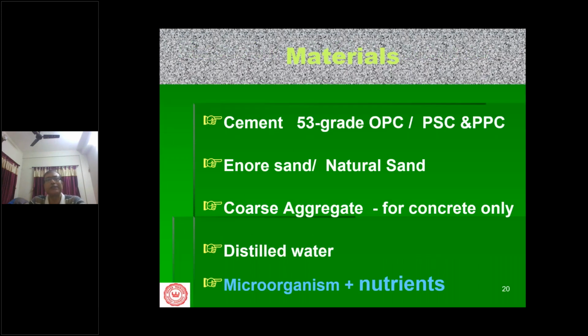Now, after getting this, we started adding it within the concrete and the mortar both, and we tried to measure the strength improvement or tensile strength at different ages, and we got positive results. For that, we used different cements, 53 grade and OPC. We also used Portland slag cement and Portland pozzolana cement. We tried with Ennore sand, natural sand. This is a step-by-step procedure. First we started with mortar, then we went to concrete. Most important, we used distilled water, and naturally the microorganisms and the nutrient.